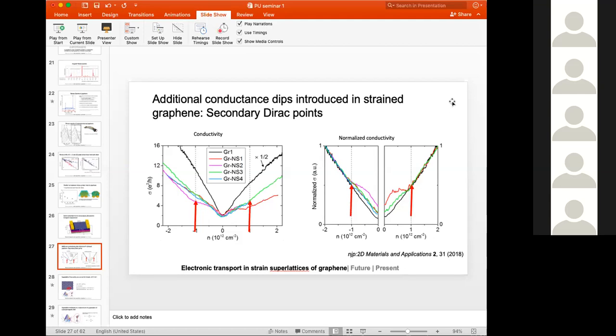Like, this is a very prominent feature which shows up in all the nanoparticle system, graphene nanoparticle system. I think this trend is pretty obvious from these graphs, but I guess what you mean to say is how are we saying that this is not due to some other effect in the system, some other impurities, some other source of those kinks, and just this strain and superlattice? And I guess the answer to that is that if those were coming from other sources, they would have varied erratically in all of these systems, and they shouldn't have shown such a consistent behavior, which is why we're attributing it to the strain coming from the nanospheres.